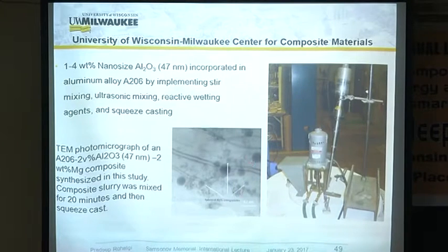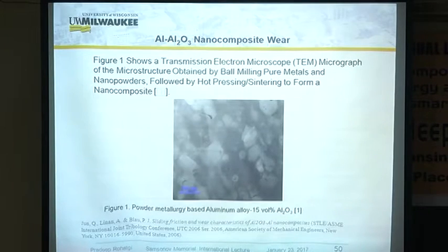Now, very simple, the same technique that we were using here 48 years ago, Mr. Prithipal Singh was running the foundry. I think it's been disbanded now. Same kind of thing, a little melt here, a mechanical stirrer and an ultrasonic stirrer, and you produce a nanocomposite. These are nano size, 47 nanometer particles of aluminum oxide dispersed in aluminum. So it's a very simple technique that you can produce these nanocomposite materials.